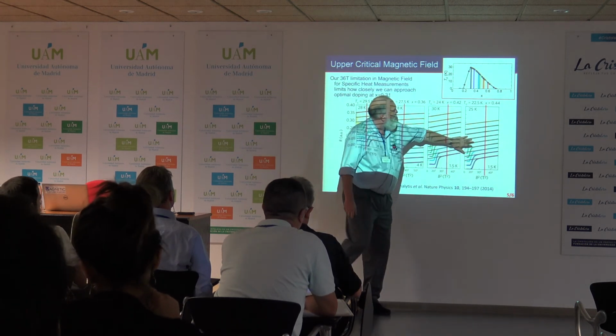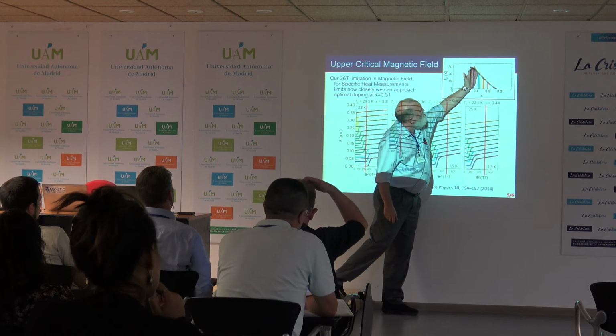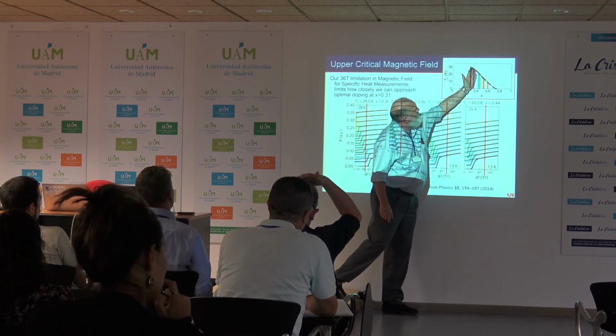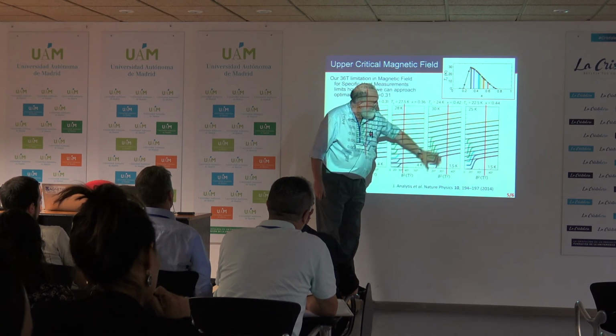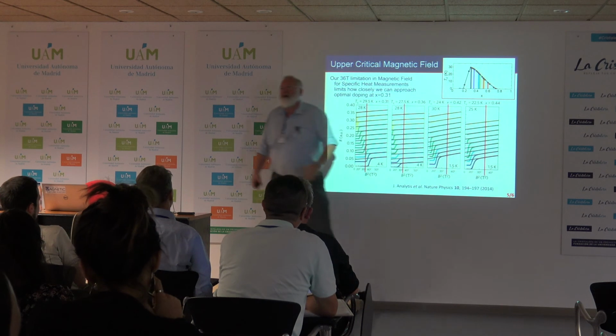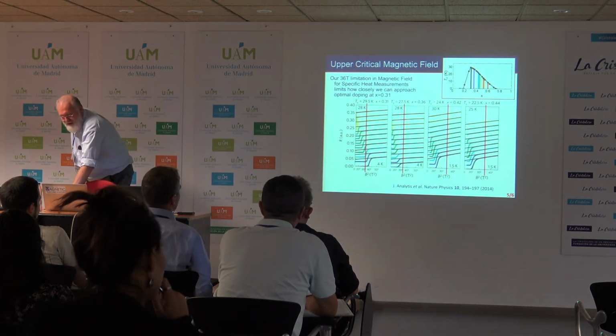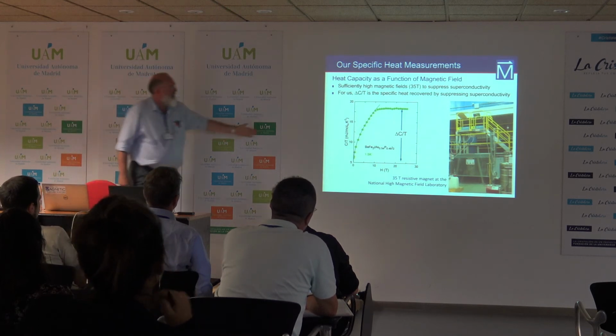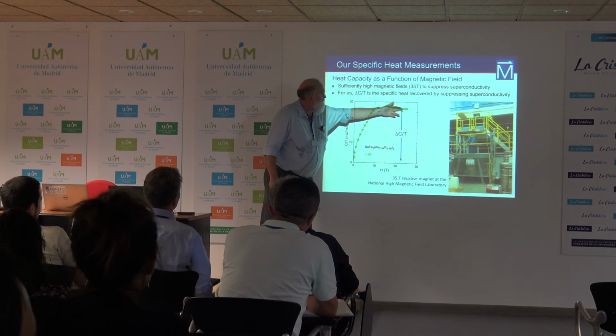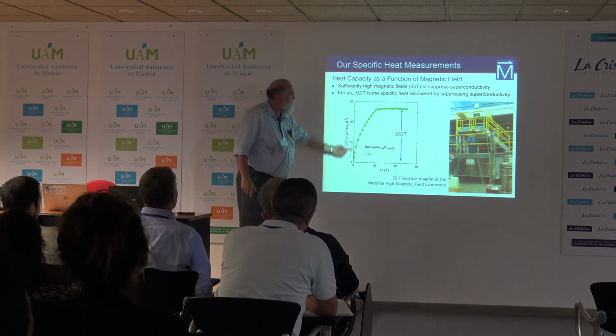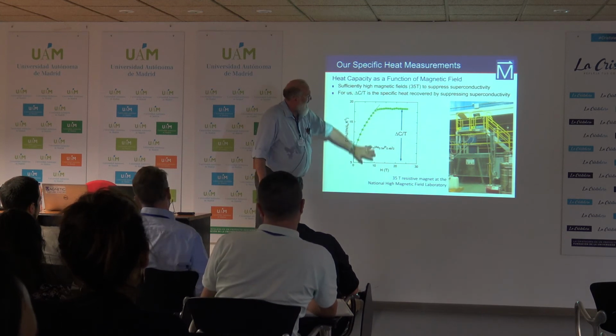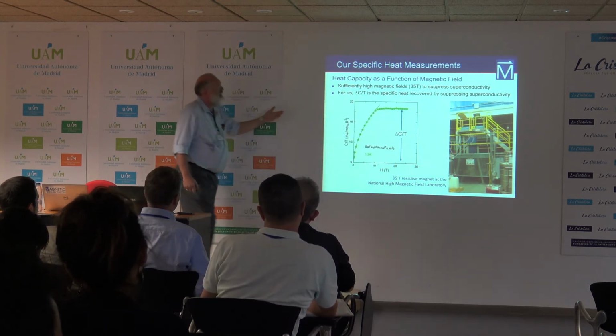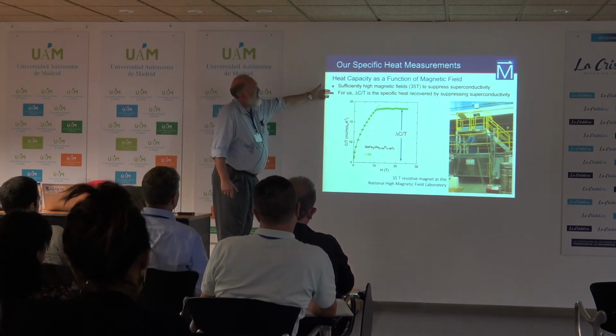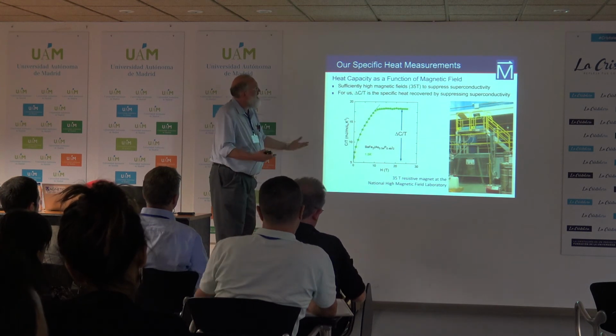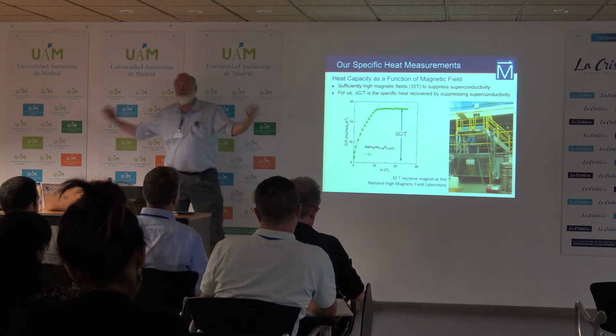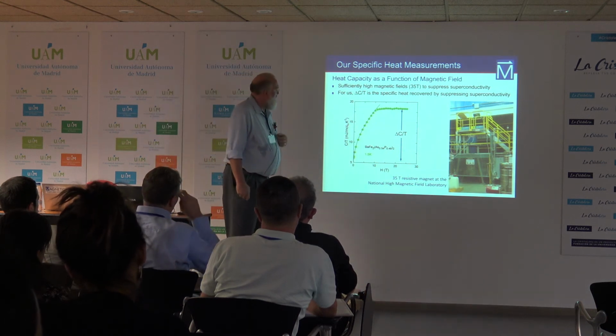But as you move to more overdoped samples over here, in this range, so for these 5 samples, up to that point, we're able to have enough of the normal state below 35 Tesla that we can measure the specific heat as we apply a magnetic field. And there's a reason that we want to do that. It becomes a relatively clear message that what we're measuring is the change in specific heat as you apply a magnetic field, and therefore you're measuring the recovery of density of states by suppressing the superconductivity. And so we're limited in the doping range, that's the negative thing, but we're measuring the total density of states from all of the bands put together that is recovered by suppressing the superconductivity.